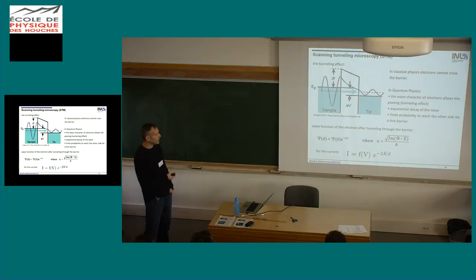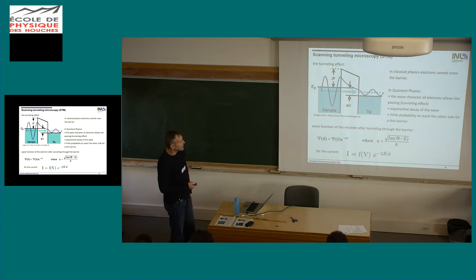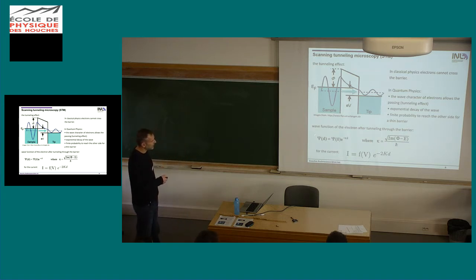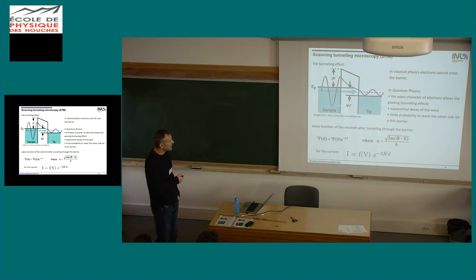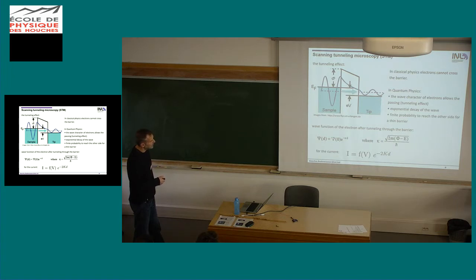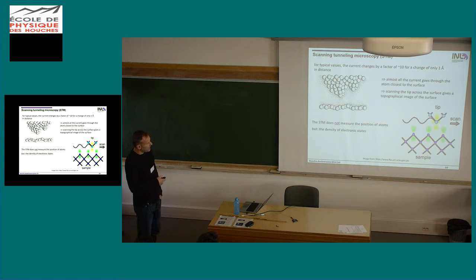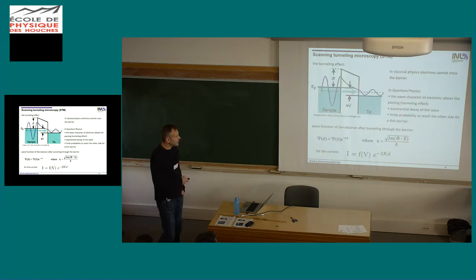The observable, which would be the presence of the electron in the tip, is related to the square of the wave function. So we have the wave function that decays exponentially outside of the material, and in this kappa we enter the barrier height, and d is the barrier width, so it's the tip-sample distance. Kappa includes essentially the barrier height. If d is small enough, there's a finite probability to have the electron tunneling into the tip. If we square this, we get this exponential behavior for the current, which is the one we want to measure. So it's scanning tunneling microscopy, and we measure the current. This exponential behavior is very important because it essentially determines the resolution.